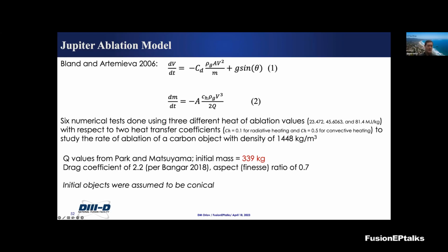So Chris did a few numerical tests using different heat of ablation values in these models, using different heat transfer coefficients for radiative heating and convective heating, to study the ablation of a carbon material meteoroid entering the atmosphere, with a density of 1448 kilograms per meter cubed.